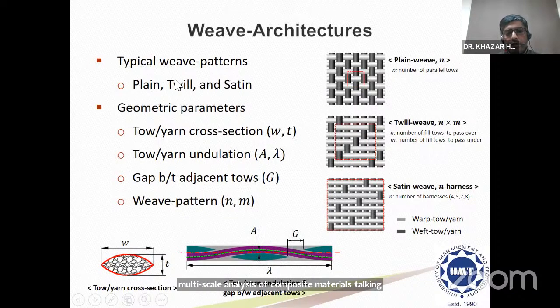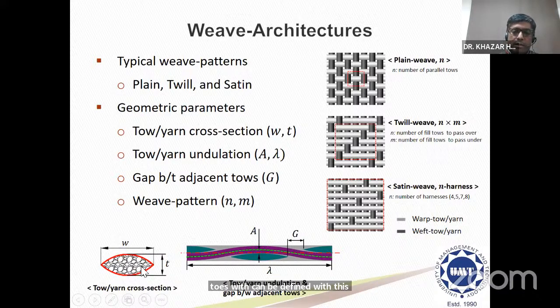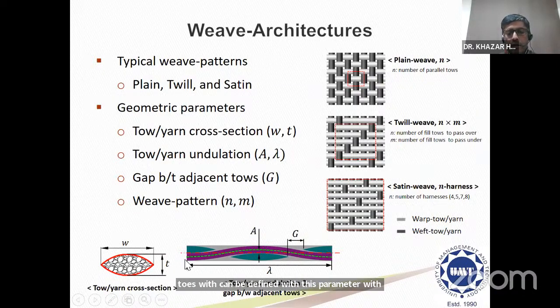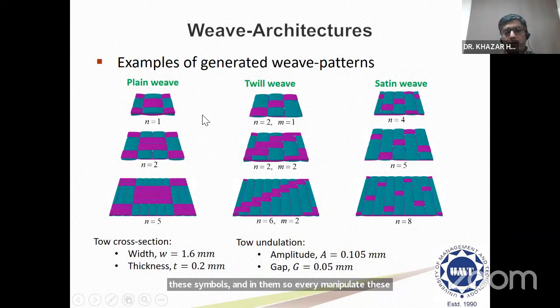Talking of woven fabric composites, typically there are three types of woven fabric available: plain weave, twill, and satin. And those woven fabric geometrical patterns can be described in terms of geometrical parameters, like the tow width, which can be defined with the parameter width, and we can also describe its thickness using the symbol T. The undulation can be described with the amplitude and a wavelength parameter, and the gap between different tows can be adjusted with the tow adjustment gap parameter G, and different weave patterns can be controlled using the symbols N and M. So if we manipulate these parameters, then we can generate various kinds of weave patterns. So here are some examples.